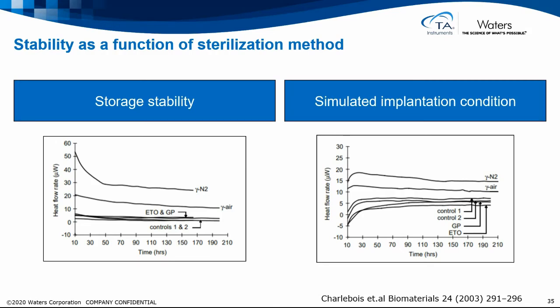And then the right example is simulated implantation condition, where it's at 37 degrees and with a buffer of body pH. We can see that the reaction rate has gone up slightly also for the control and the GP and ETO sterilized material, and the reaction rate in the gamma radiation is still higher than the other.